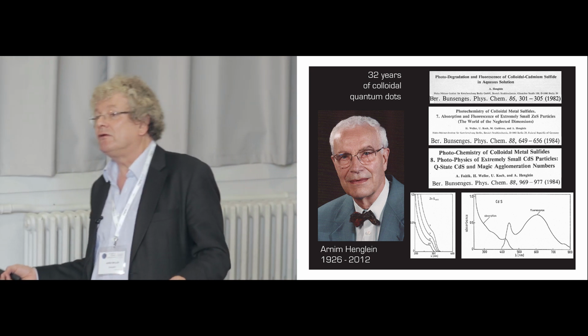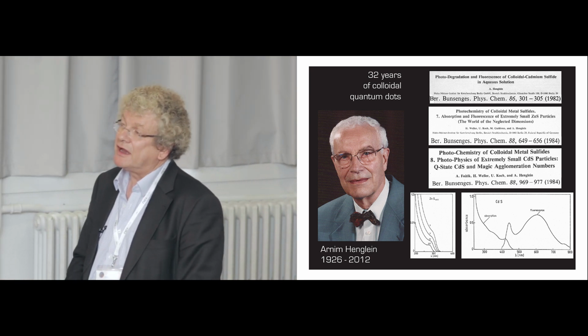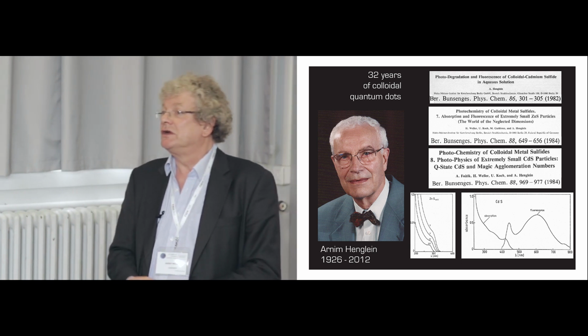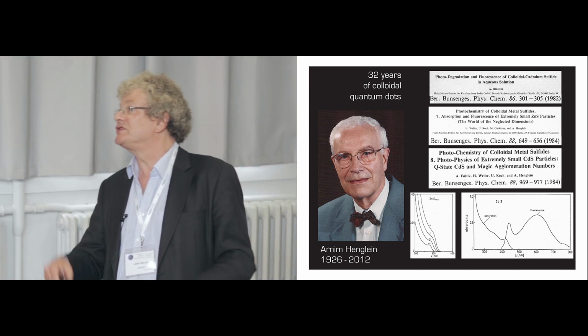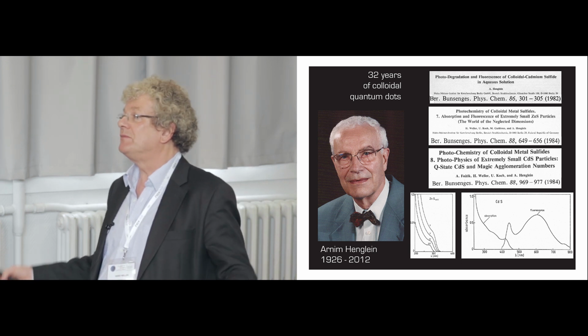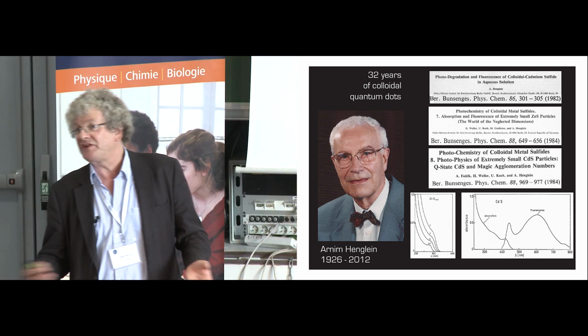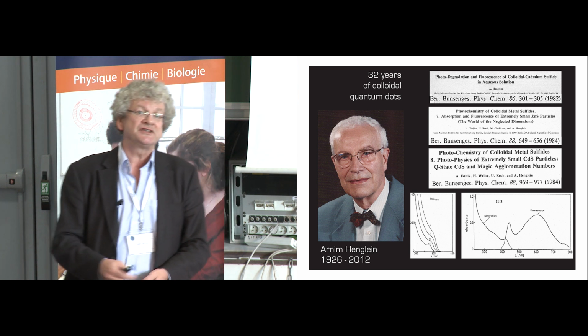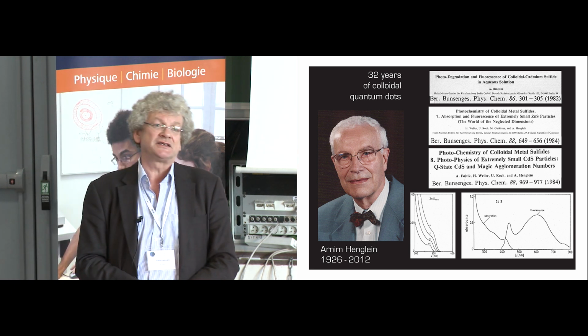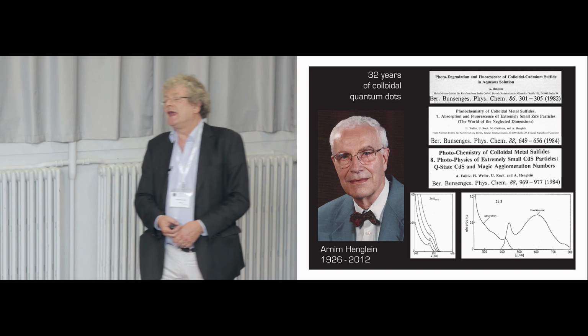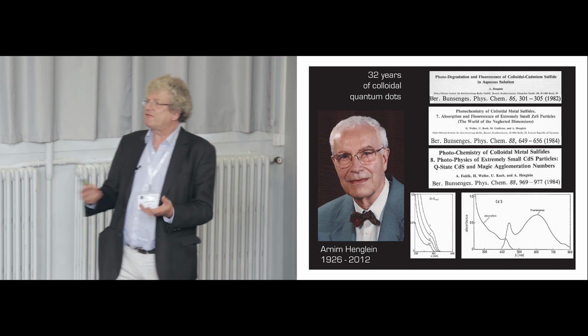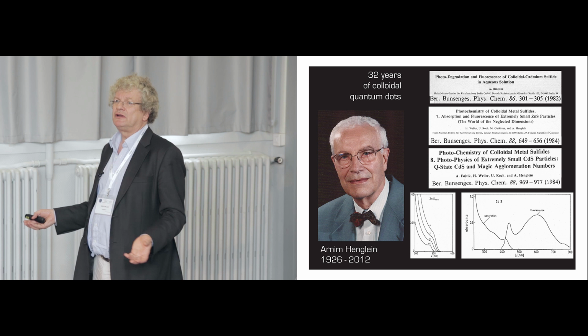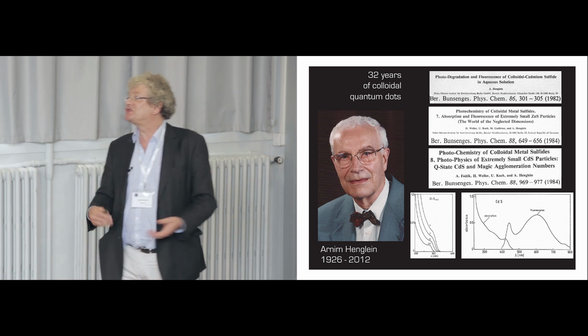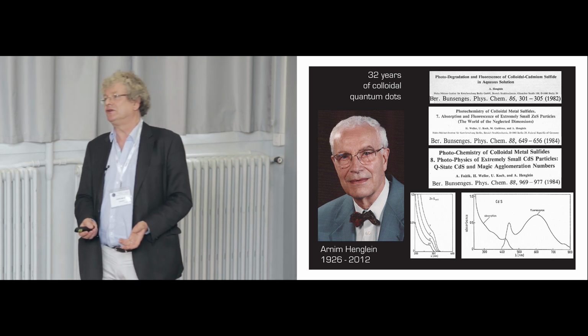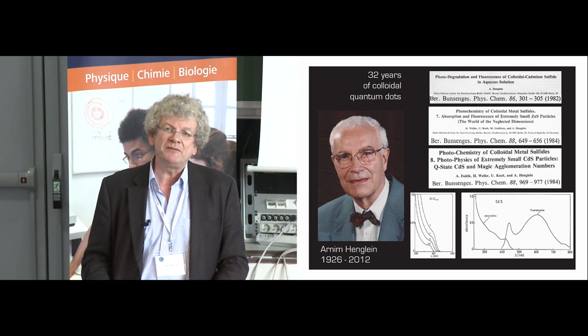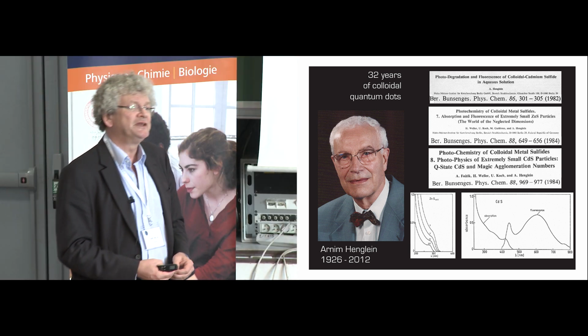They investigated also inorganic substances like silver ions, which become reduced by one electron to a silver atom, and then many silver atoms come together forming silver clusters. At that time, they saw already all these things changing redox potential as a function of size. And finally, if everything is consumed and you have formed your colloidal particles, then the electrons charged the silver and hydrogen was evolved. And that was just during the time of the second oil crisis when they did this.